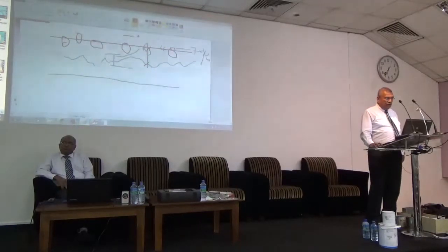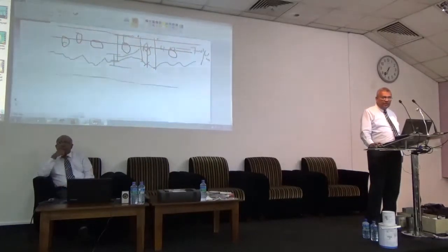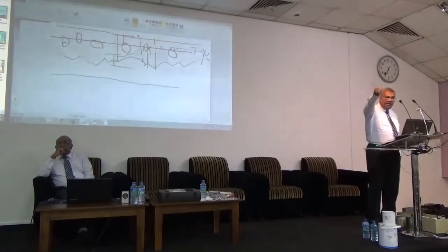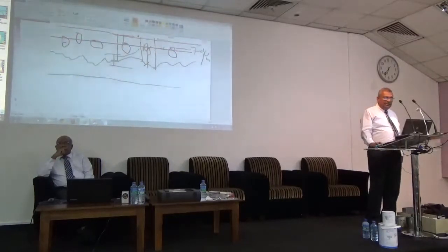So then tomorrow you don't think about it, you put the next coat. Now here you have 100 microns. Now here you have 150 microns. But here you have only 50 microns. There are going to be failures there, spot rusting, because the required DFT is not there now.